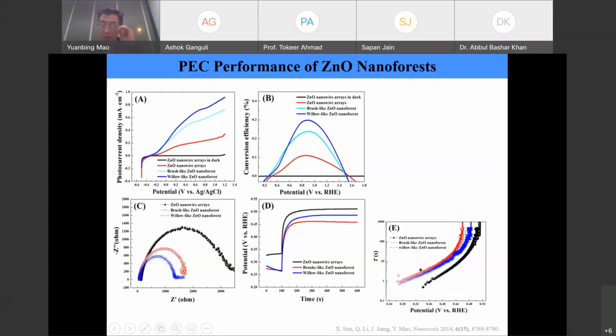So that also helps us understand why the nanoforest samples have higher conversion efficiency. While here, if we pay closer attention, you will see that in terms of the decay time, the brush-like nanoforest actually has a shorter time compared with the willow-like. We believe that for the willow-like nanoforest, the branches are too small, so they could have higher defect density, and because those branches are attached to each other, that also provides the possibility for the charge carriers to recombine in the willow-like nanoforest. So that's why there's a little bit of difference here.